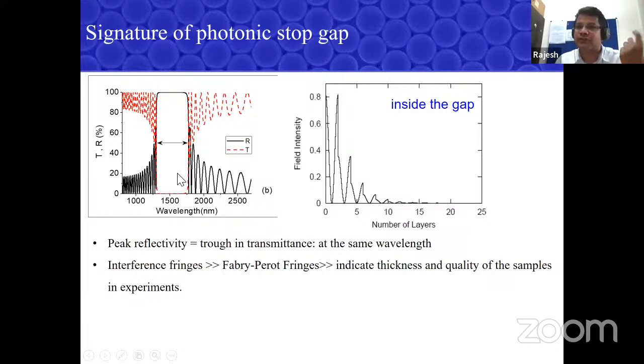The band gap position depends on the refractive index contrast, that is the difference between epsilon1 and epsilon2 from my previous slide. The larger the difference, the stronger the light-matter interaction. If you look at the field intensity inside the structure, suppose you launch light at a wavelength around 1500 nanometers, you can see that the field has an exponential decay into the structure. Why the exponential decay? Because this is the band gap wavelength, so the light cannot propagate into the system. It is actually damped.